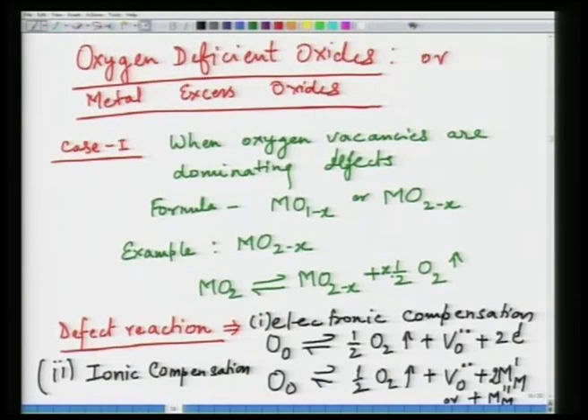And then we took various cases starting with oxygen deficient or metal excess oxides. And case one was where we took oxygen vacancies as the dominating defect, and we established how the defects can be formed. You can have electronic compensation of defects, or you can have ionic compensation. Basically, in both of these cases, you will have formation of oxygen vacancy coupled with either formation of electrons, quasi-free electrons, or reduction of metal on metal site.